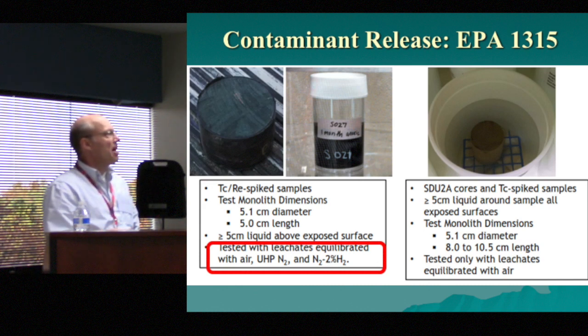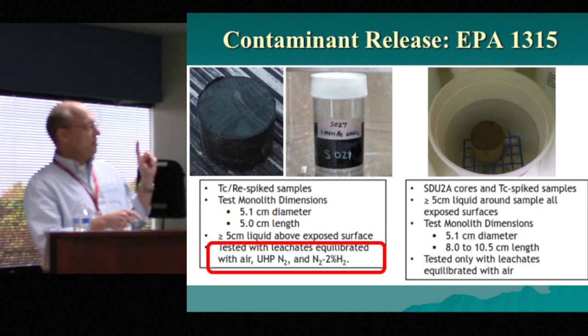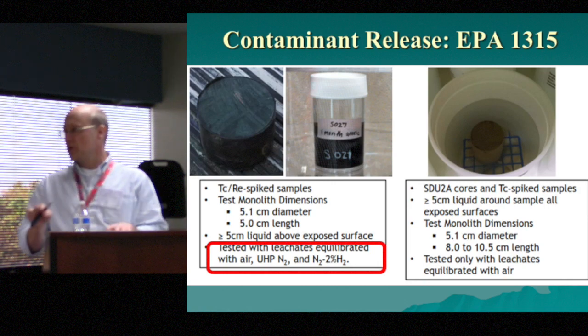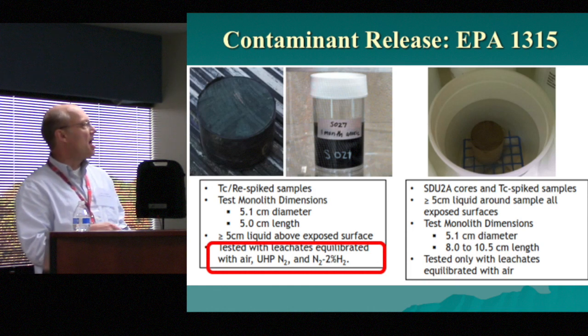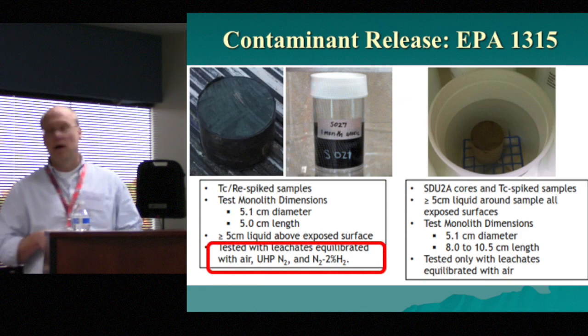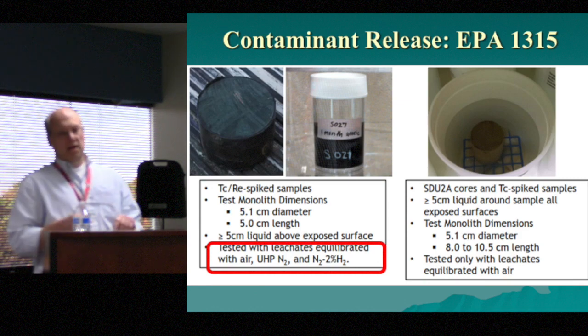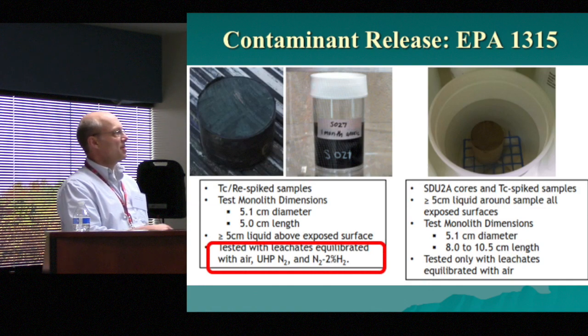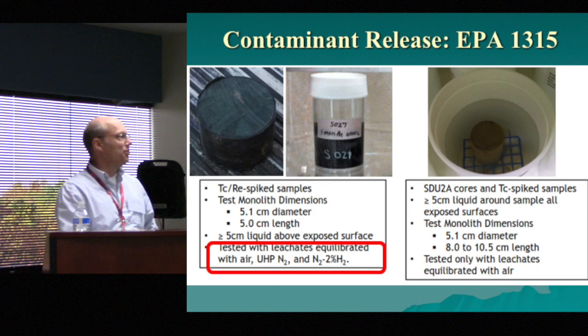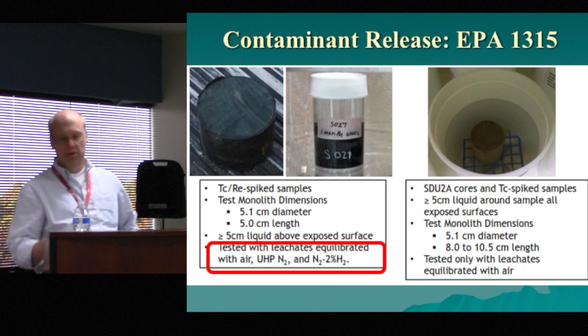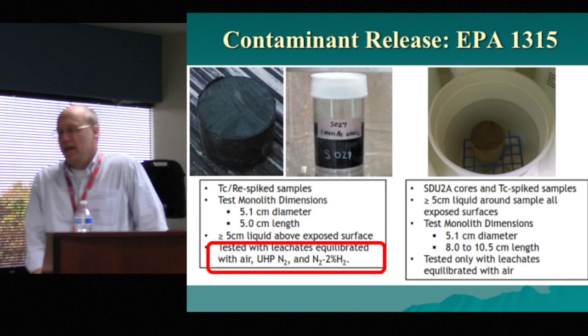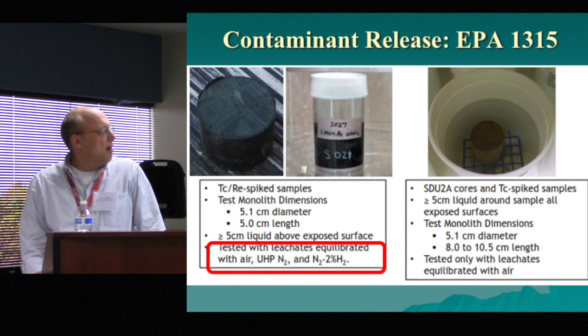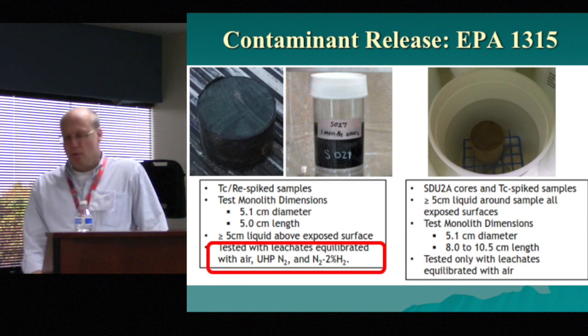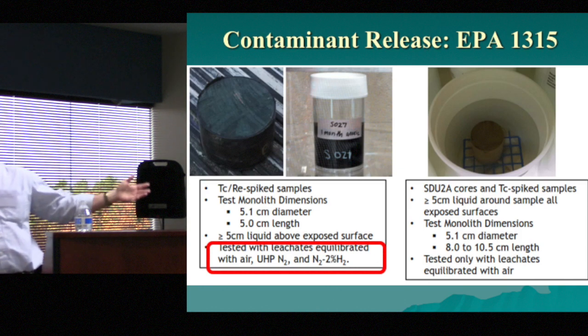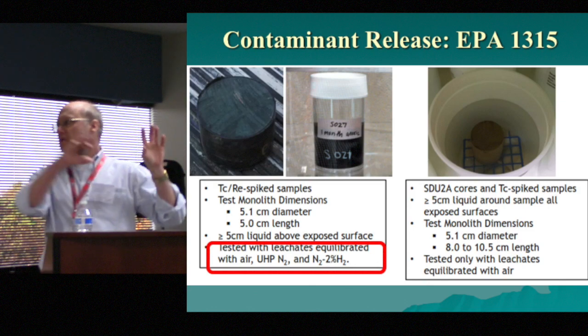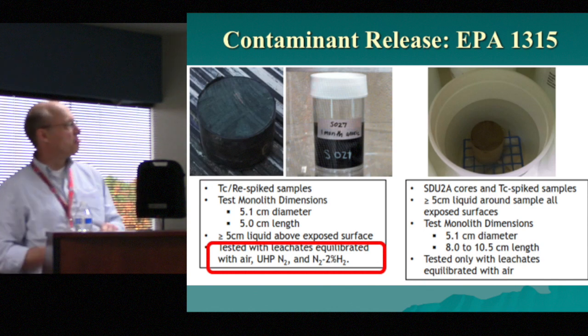And so because we're exposing about 20 cubic centimeters, the EPA test actually says what the solid to solution to exposed surface ratio has to be, and it's a 9-to-1. And so the sample is down in here, and it's actually in 180 mL of water surrounding it. Now, what's unique about what we did is we also did this test under 3 different atmospheres. We did it under ambient air, ultra-high purity nitrogen, and a nitrogen-hydrogen mixture that you often use in glove chambers to keep the redox conditions low and make sure you have no oxygen. We took the artificial groundwater solution and equilibrated it with those atmospheres before we put it into the sample, and then we also put all of these samples inside the chambers to make sure that the atmosphere around the samples was consistent with the water that it's being exposed to.